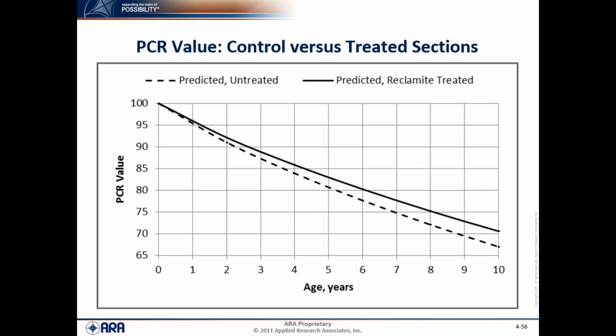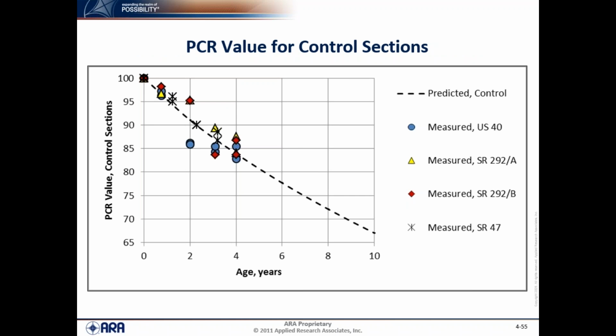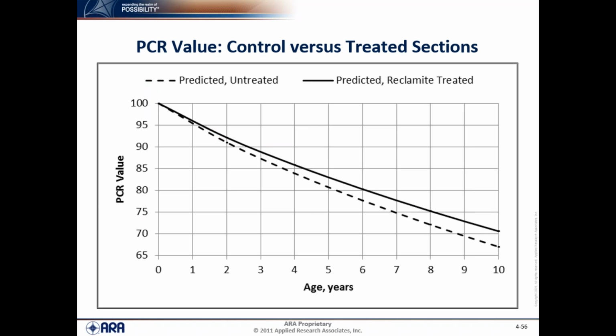And this just shows the two that had the major differences. The predicted line for the untreated or control section is the dashed line. The solid line is the average predicted for the Reclamite treated sections. And you can see in the report we used a PCR value of 75 to initially define what the differences were. So the difference makes about a year. If we were to rehabilitate or do something to the pavement at a PCR of 75 on the average, then we wouldn't have to do it on the Reclamite section until about a year later.